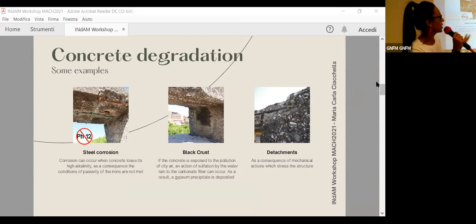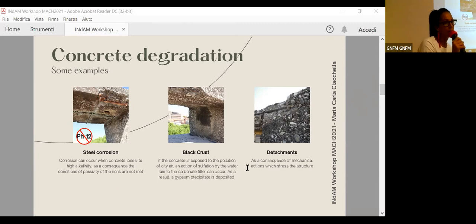Here you can see some examples I faced in the last works. Corrosion occurs when the pH is no longer at 12, so the high alkalinity is lost, and as a consequence, the condition of passivity for the bars is not met. Another example is black crust, which is very common in our city, close to, of course, the pollution. The action of sulfation by rainwater can cause the precipitation of gypsum. This is not only a static problem, because when the crust grows, the thermal mechanical behavior of the crust is different from the substrate, and this can cause detachments, which are more in general a consequence of mechanical stress on a structure that is not able to absorb it.